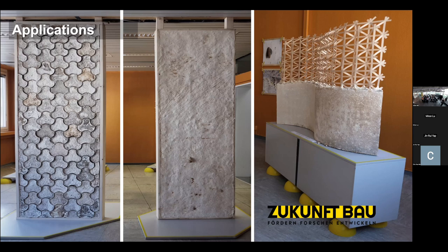One is fully grown in one frame, and for another one we use tiles. And we also reinforce it with wood to test basically the acoustic performance of the material under different circumstances. And the result was promising. So the application for such walls is for a place like here to help us absorb sound for office spaces. So the test that we also did was for the sound ranges for normal office spaces, not for highways, for example.